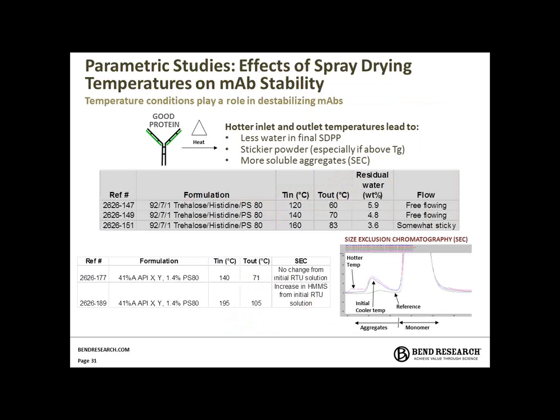This slide highlights the temperature conditions that were used during that spray dry process. We ranged from a T in of 120 to 160 and a T out of 60 to 83, as shown in the spreadsheet there. As Devin was discussing earlier, water content correlates with formulation as well as T in and T out conditions. One of the things we were also looking at was downstream handling, so here is flow. The higher conditions were causing plasticization of powders and impacting what we call the stickiness of those powders and handling.